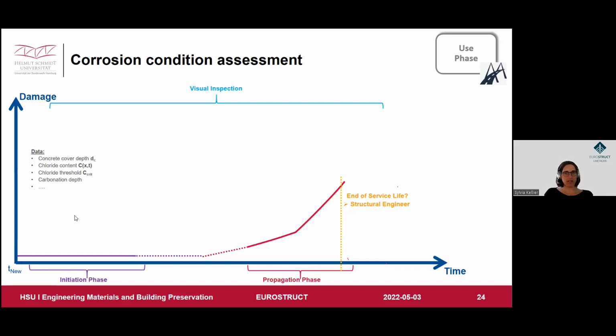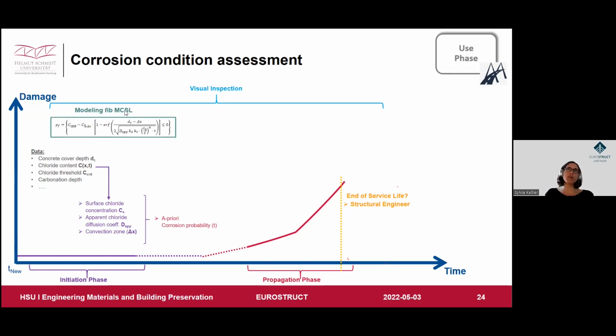What do you do with the data? Out of the chloride profile, you can get the surface chloride concentration, the apparent chloride diffusion coefficient, and you can also get a clue about the convection zone. This information enables you to calculate an a priori corrosion probability based on the model from the Model Code for service life design. And you know much better what is really the corrosion probability or the depassivation probability of your structure. These are all inspection methods which are very easy to do. For the chloride content, there is also monitoring available.